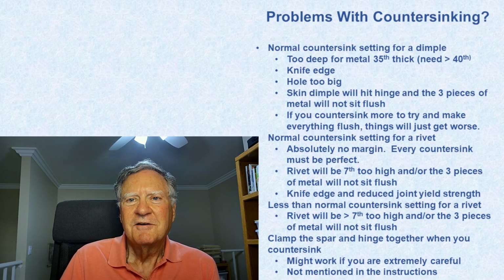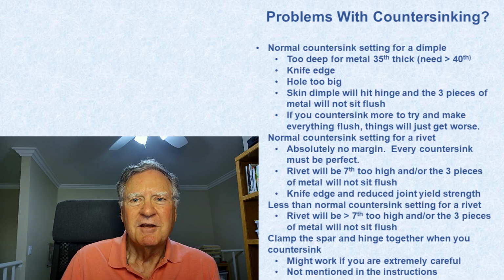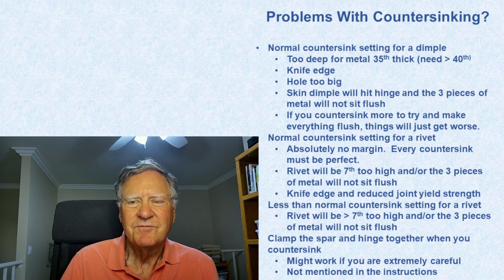And if you're observant and you notice that things are not sitting flush, you're going to be tempted to just countersink more. I mean, if you just had two pieces of metal and the bottom piece was nice and thick, that's how you would solve the problem. If the dimple is not sitting flush, you just countersink a little bit more, and then the top piece of metal will sit nice and flush. But if you do that in this case, it's not going to help, and it's going to make things worse. It could be that some of these cracks are due to people doing just that, that they're just way over countersinking.